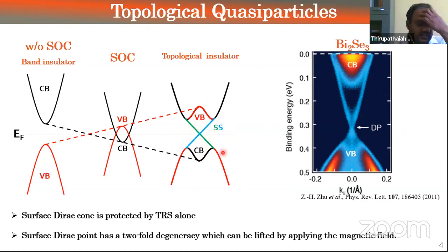There are many results which were reported. Maybe the first was found in 2007 or 2008, but I have taken one from 2011, which was a bit more beautiful to present here. So here is a Dirac point. An important point about this Dirac point is that it is only protected by time reversal symmetry, and you can open a gap just by breaking the time reversal symmetry. That means it is only a twofold degenerate point. According to the latest understanding, such a twofold degenerate point is called a Weyl fermion. So I don't know whether one can still call it a Dirac fermion rather than a Weyl fermion. Maybe theoretical people can advise, but for me it looks like a simple Weyl fermion rather than a Dirac fermion.